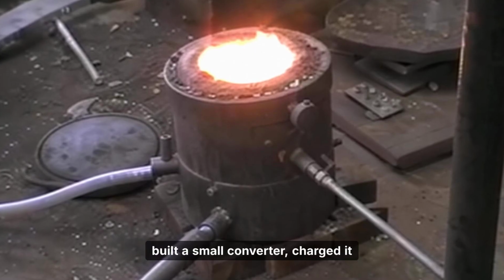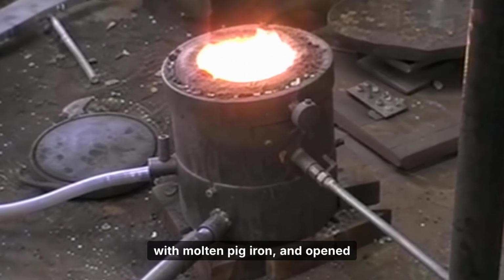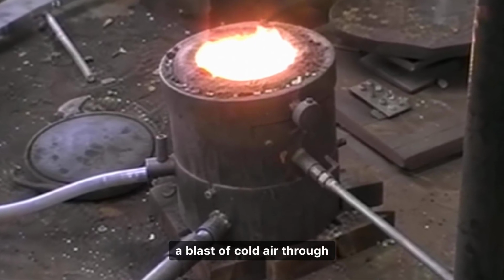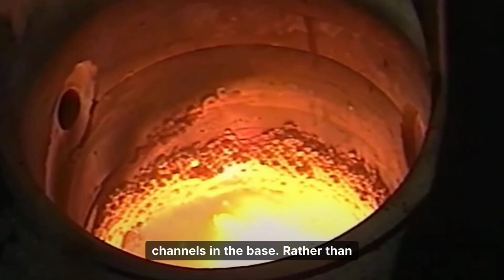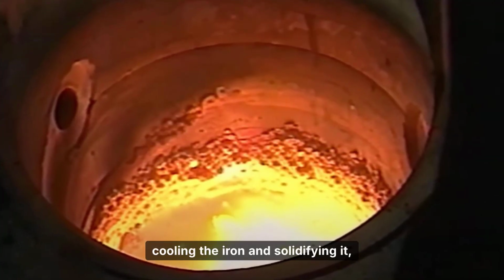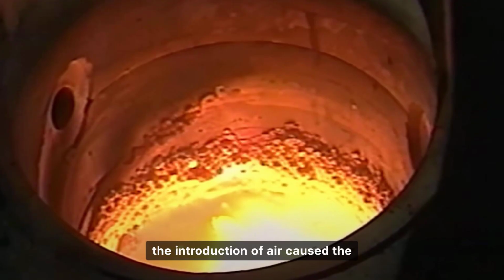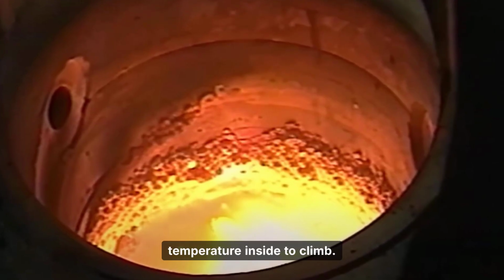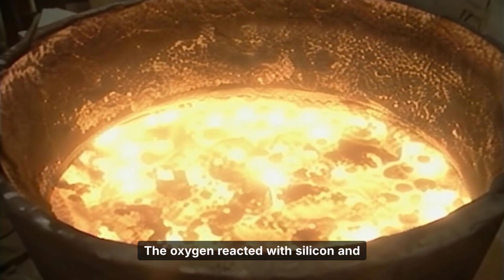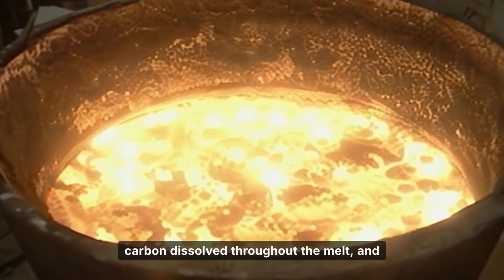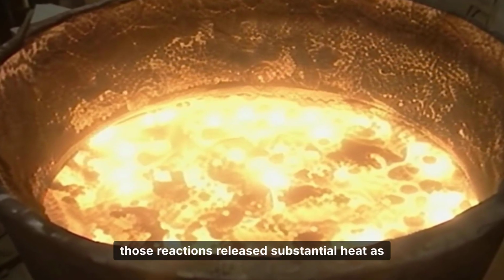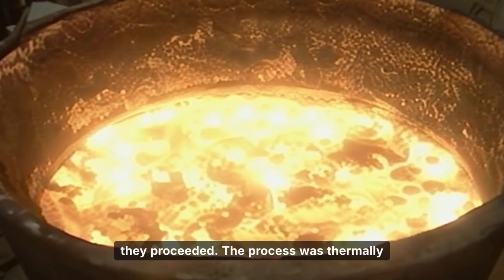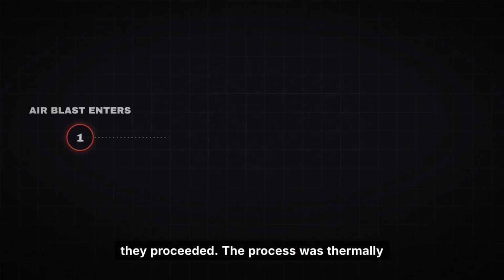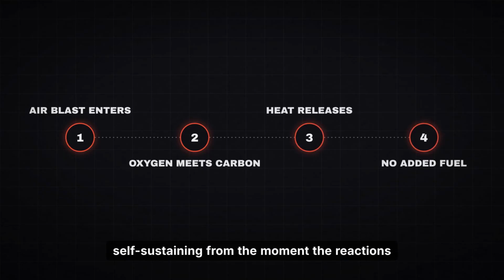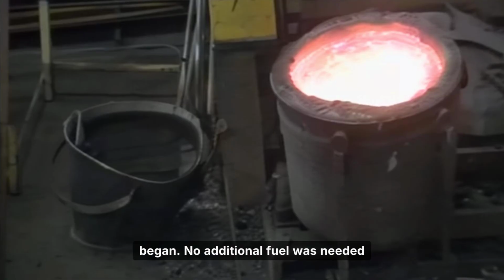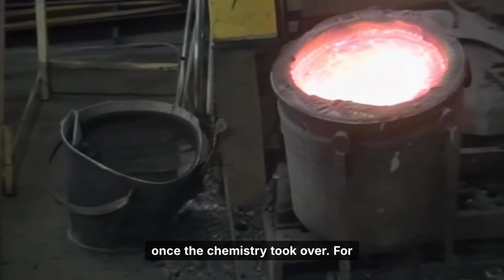He built a small converter, charged it with molten pig iron, and opened a blast of cold air through channels in the base. Rather than cooling the iron and solidifying it, the introduction of air caused the temperature inside to climb. The oxygen reacted with silicon and carbon dissolved throughout the melt, and those reactions released substantial heat as they proceeded. The process was thermally self-sustaining from the moment the reactions began. No additional fuel was needed once the chemistry took over.